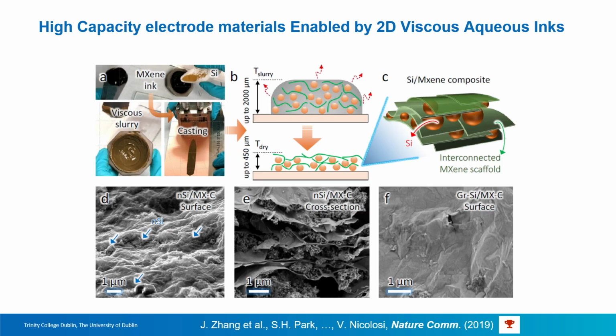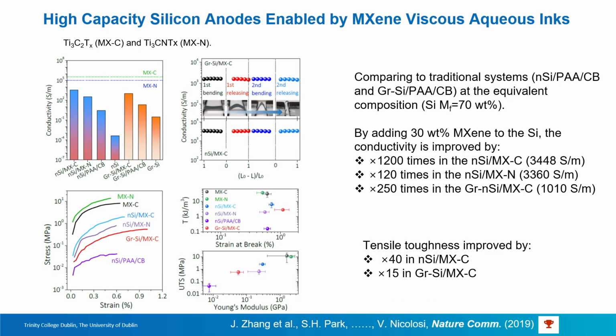What it means is that the silicon particles were completely capped and entrapped within blankets of 2D materials. And this became really the advantage. I just showcase very quickly the type of achievements that we get. By adding just 30% of MXenes by weight, we get an improvement of about 1,200 times in conductivity. We tried different types of silicon, and the improvement was substantial in all of those.